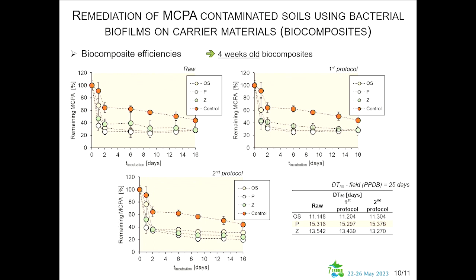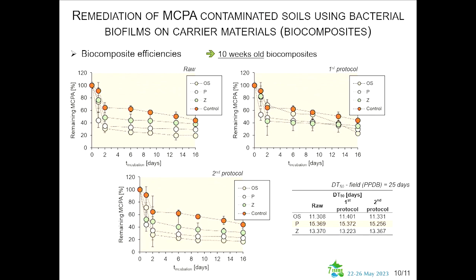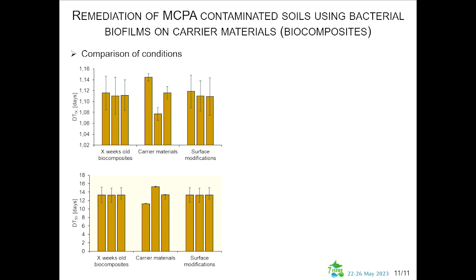I did it with the 4 weeks old biocomposites, 7 and 10. Here this DT50 is about 12 days. And we do not have the same behavior. We have in the solution worst dissipation for oyster shell, while here this is quite the inverse. I tried to compare conditions to see if a different age of biocomposite, different carrying materials, or different modification will improve the bioremediation, what would give the best results.